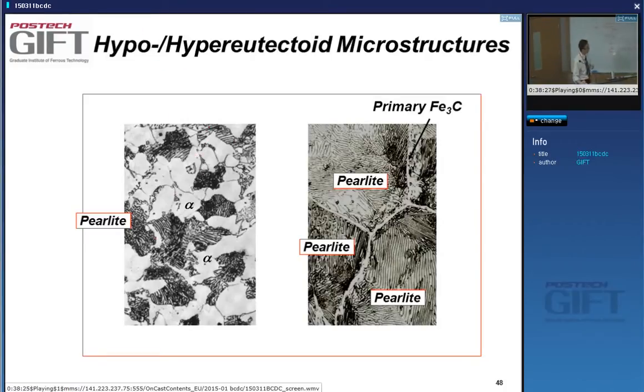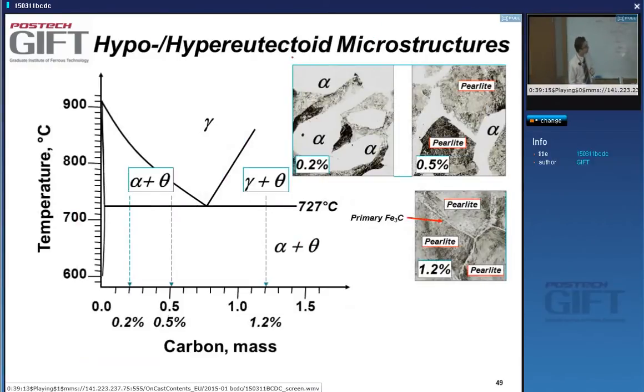the ferrite phase. So, for instance, here this is a situation where the matrix is our ferrite grains, and in this matrix you have quite a lot of pearlite. If I increase the pearlite content more, I get a situation where the matrix is pearlite. And then there's a little bit of another phase in here, which is cementite, little blocks of cementite at the grain boundaries. But basically, we're still dealing with ferrite and cementite. Yes, but the microstructure is different because of the eutectoid transformation. So let's have a look at trying to understand these microstructures.